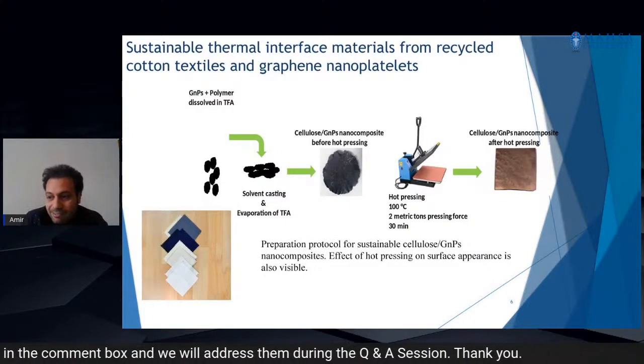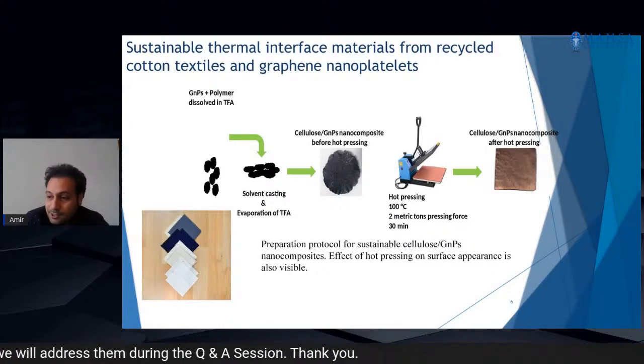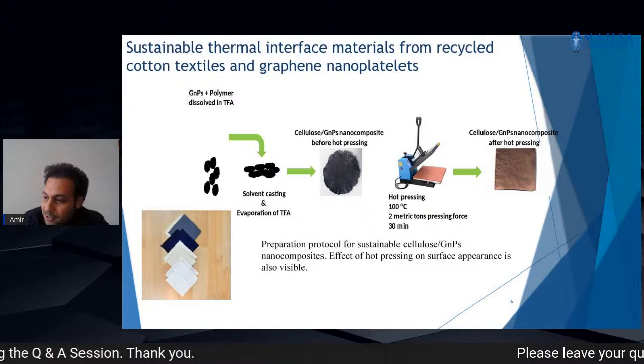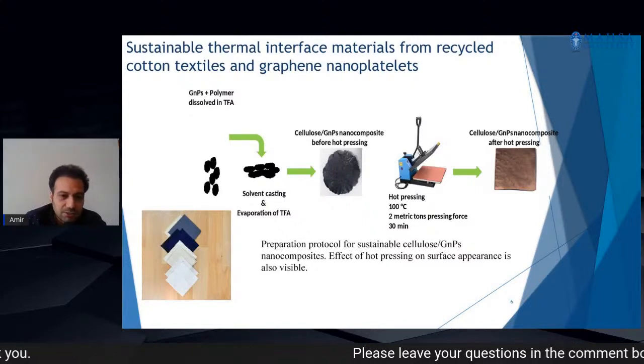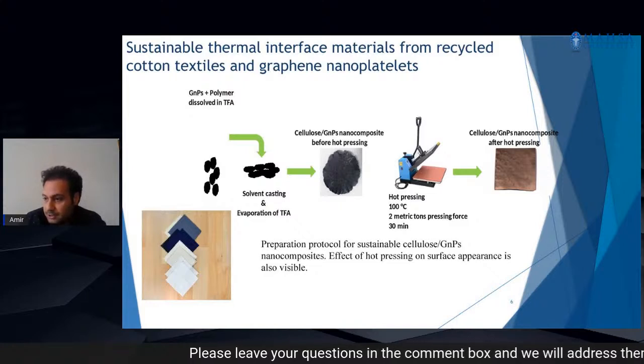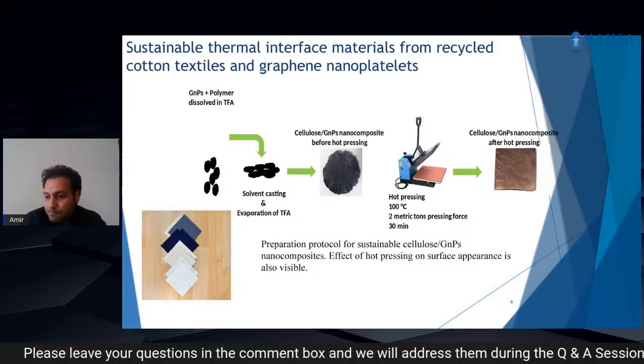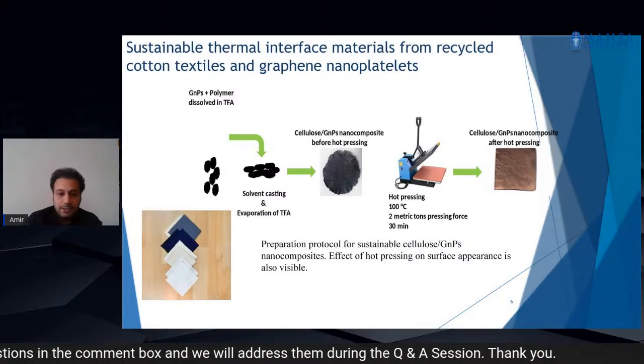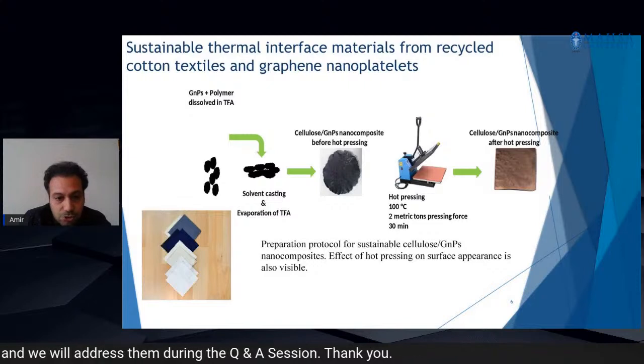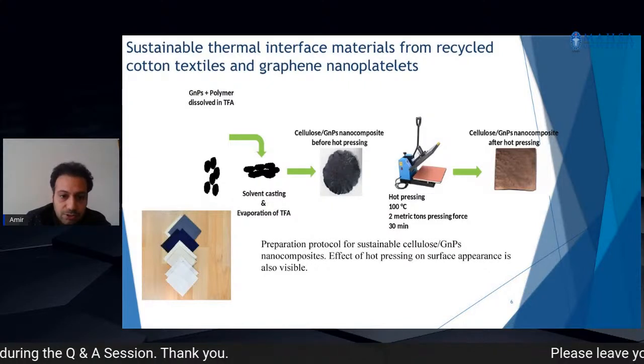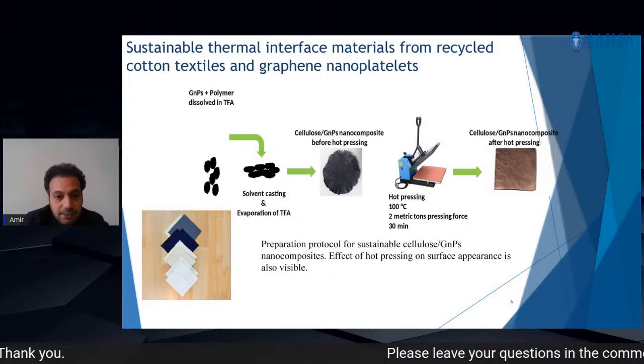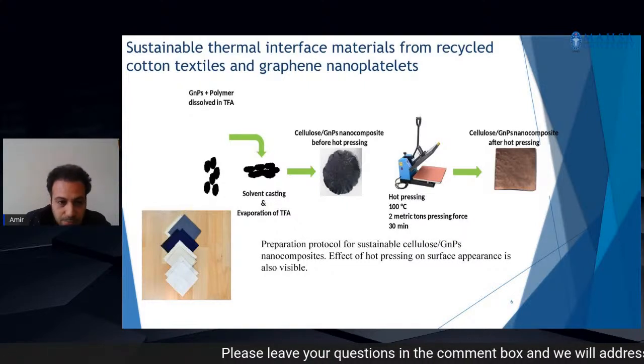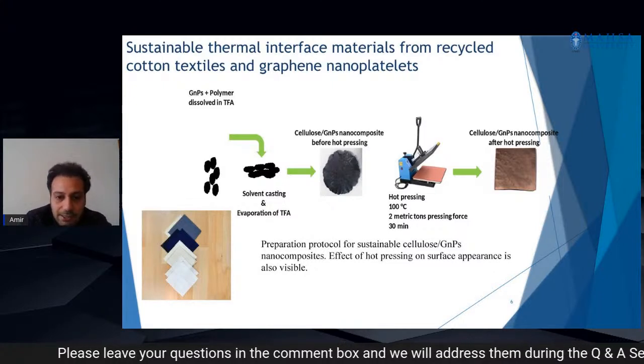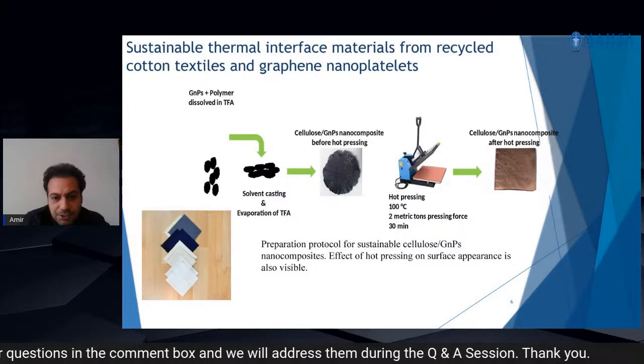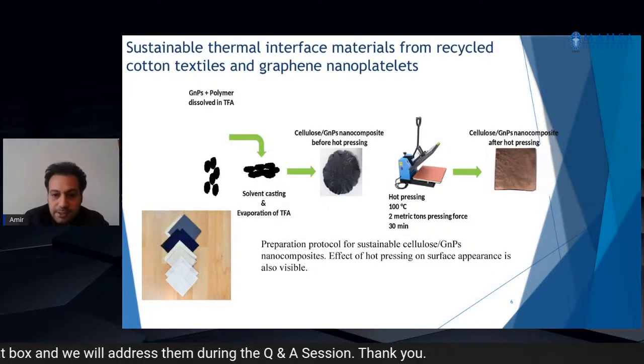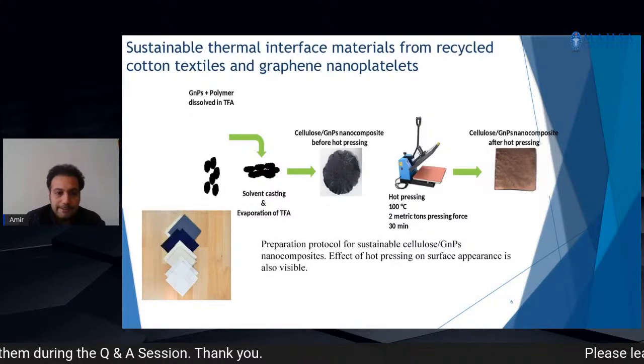A commercially available thermal pad and clay putty were used as references in this paper, with a thermal conductivity of around 6 watt per meter Kelvin and 1 for these two. Here, just to show you, first of all, we are trying to dissolve the material in the solvent, in the TFA, and then with the process of hot pressing, going to around 100 degrees, make the samples, and then analyze all of them with different instruments.